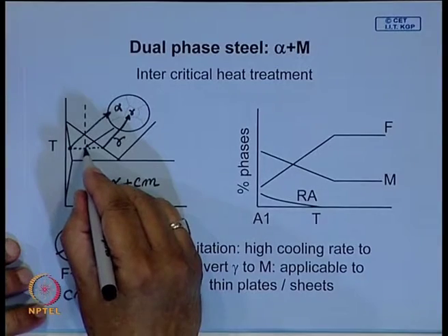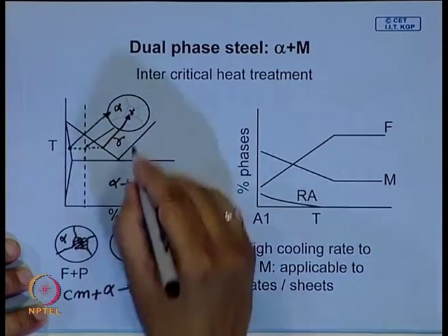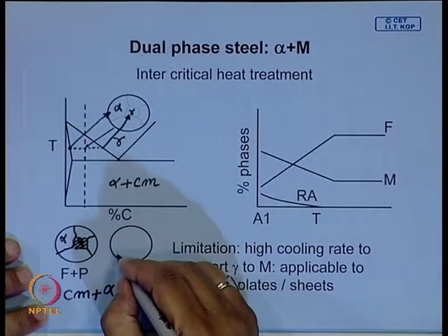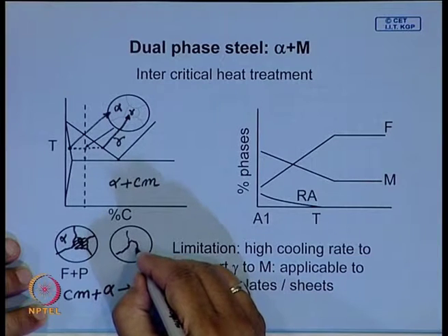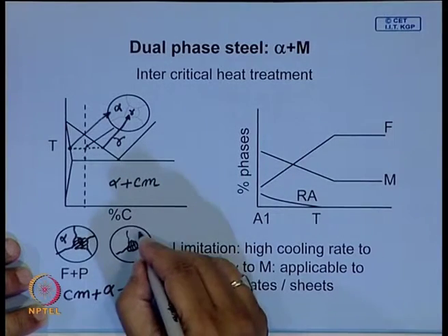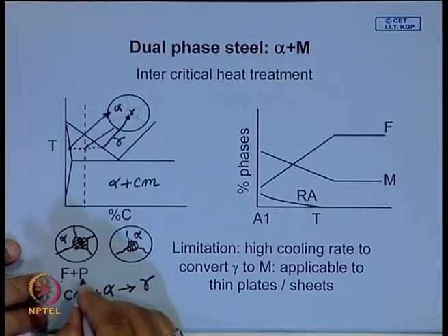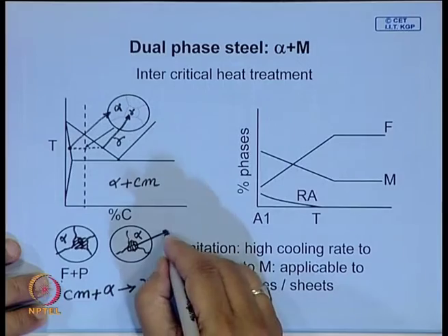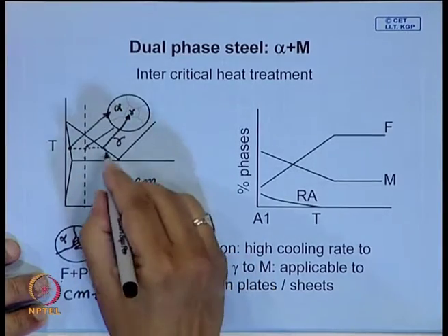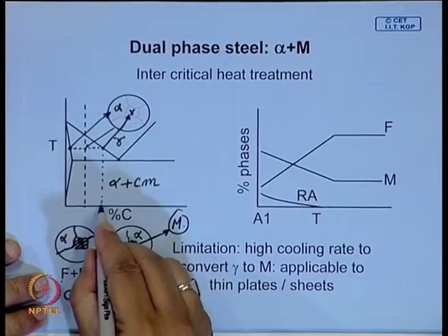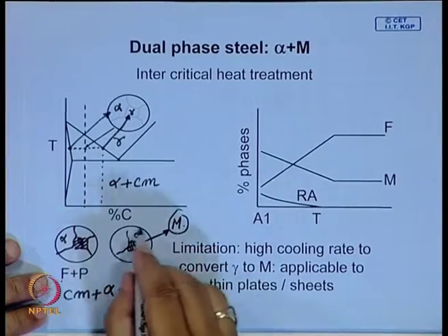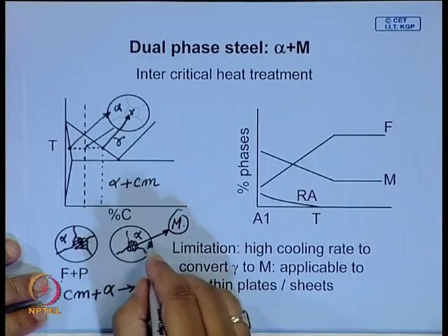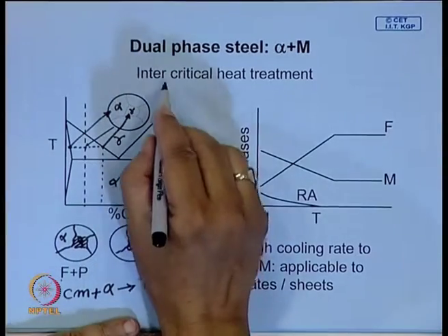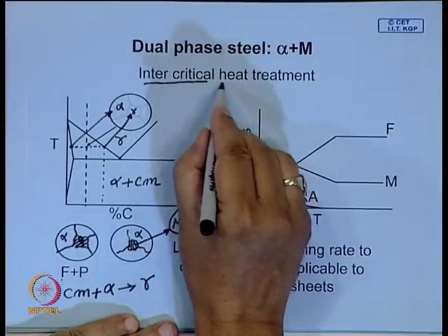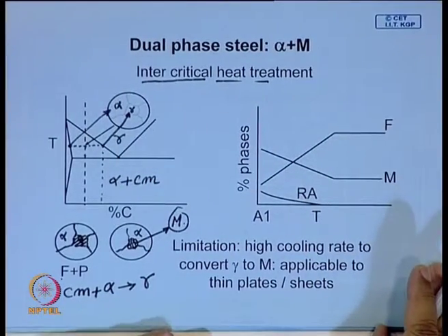Now, what will happen? Suppose you quench from here. Then the ferrite parts will remain unchanged, but the austenite part will convert into martensite. Then, instead of a ferrite pearlite structure, you will get ferrite martensite. Since its carbon content is high, this martensite will have very high hardness. So, you have a sort of composite material, a two phase duplex structure. This is the advantage of this intercritical heat treatment, and it can be implemented in mass production as well.